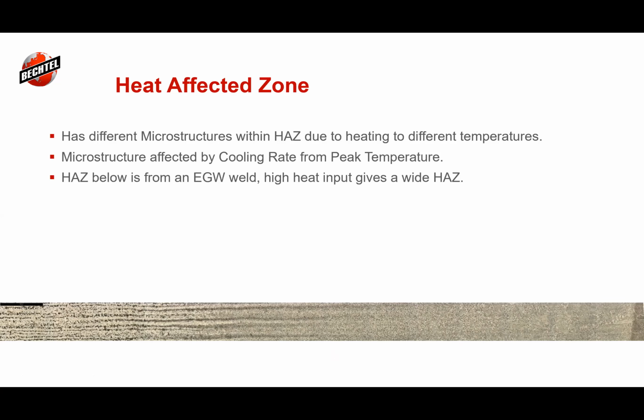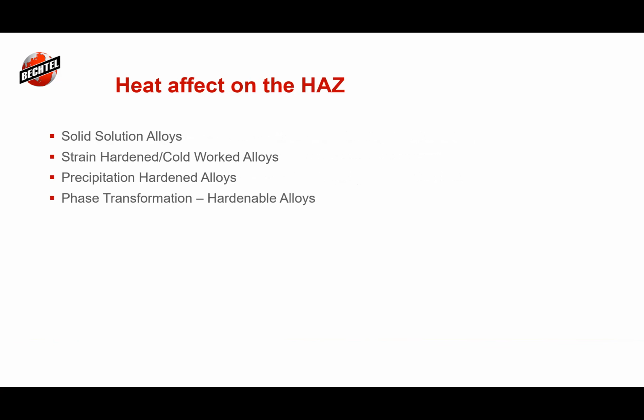What's nice about it is, for example, it's easy for me to show all of the different phases. But when we weld with gas tungsten arc welding, or if we weld with gas metal arc or stick welding, all of these same changes are occurring just in a really small package that's really hard to distinguish. But that still means that we have different areas of that heat affected zone that have reached different temperatures. And this is where slight changes in the amperage, the voltage, slight changes in even the weave procedure, if we differ from the welding procedure specification where it was tested, can have drastic differences on what our final weldment properties have out in the actual application.